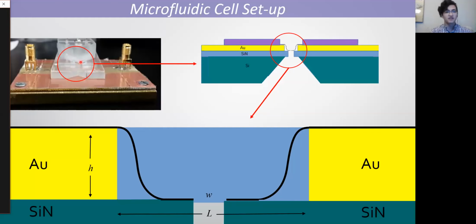no interference. After everything's connected, we are able to measure the IV characteristics, and we should see a completely isolated system. So there's no current going through because the graphene has yet to be broken. To actually facilitate the breaking of graphene to make the nanogap, there's two primary ways that we use in our lab. One is via capillary-induced breaking. That's where we use the capillary forces, knowing the height of the gold and the distance between the gold electrodes. We're able to use capillary forces to break the graphene and cause a very specific gap in terms of its distance. This method has been used in the lab in the past.